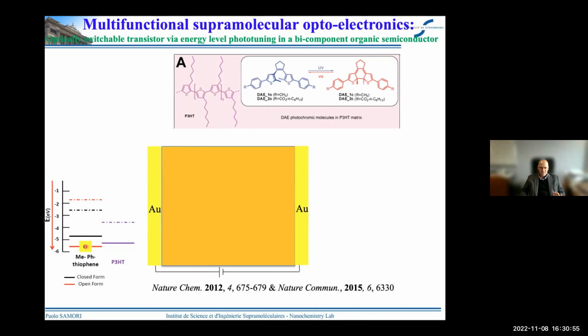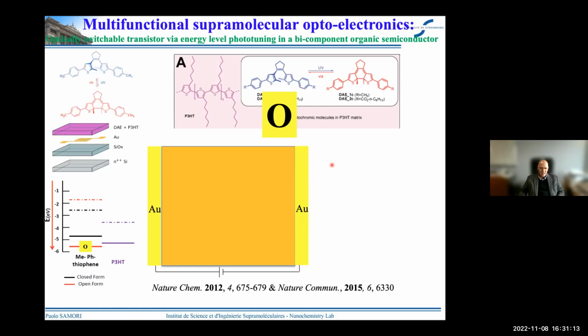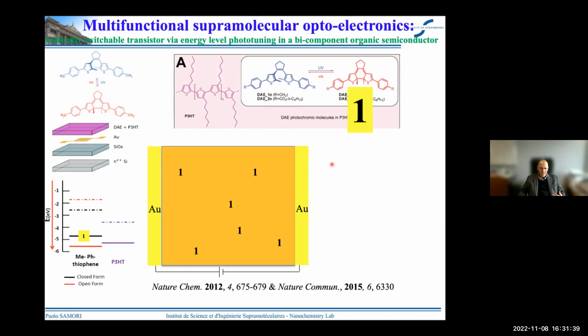So overall, we have designed a system such that the closed state can act as a trap, and the open state as a non-trap, for the charge transport in the P3HT film. We have then dispersed our diarylethene in the channel of our semiconductor, that is filled with our P3HT. When it is in the open state, indicated with zero, if we illuminate with UV light, with high power, we can trigger the isomerization of all the zeros into ones. Therefore, we are creating traps, and the charge will not flow as nicely as it did before. And then we can release with visible light and go back to the initial case.